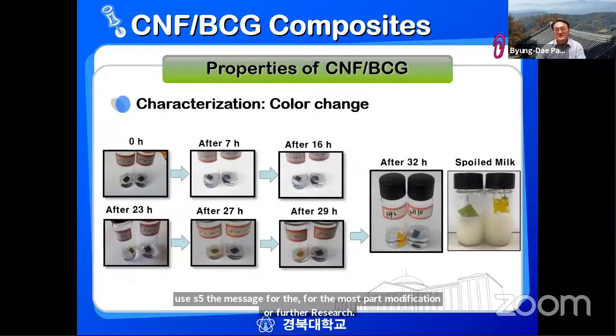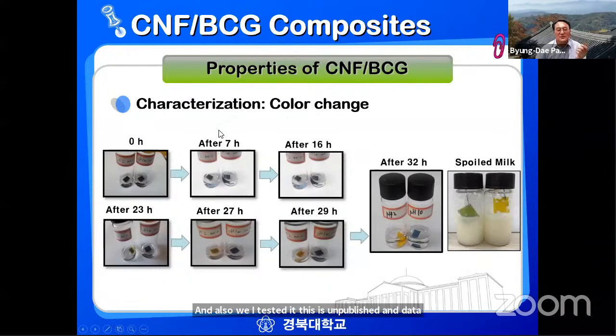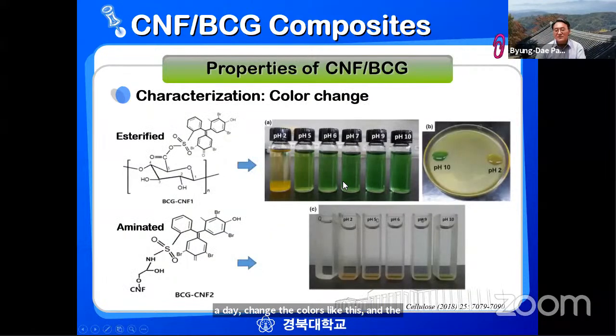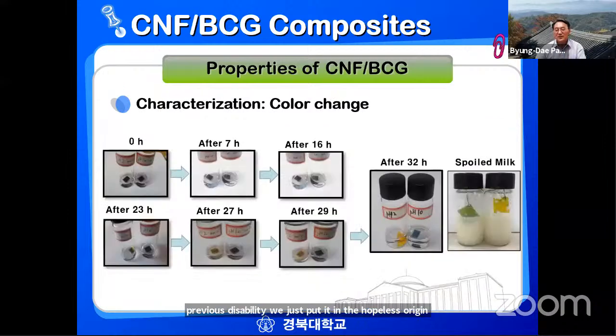And also this is unpublished data, but we prepared the films and then put them in pH 2 and pH 10 solutions, and kept them for up to 32 hours. They change the colors like this, the film and the purple solution. In previous research we just put it in the purple solution as particles, but here we prepared the film in cellulose acetate, and then they change the colors in 32 hours. Actually it changed at about 27 hours.